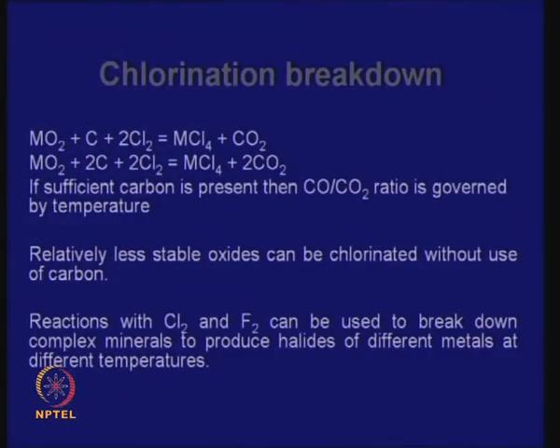We are discussing extraction of titanium from ilmenite. We have talked about three basic routes. One is where we smelt ilmenite in an electric furnace using carbon as a reductant — we produce pig iron, and if there is some chromium and vanadium in the ore they also go there, while the TiO2 part goes into the slag. We get a titaniferous slag, and from that slag we extract titanium by chlorination.